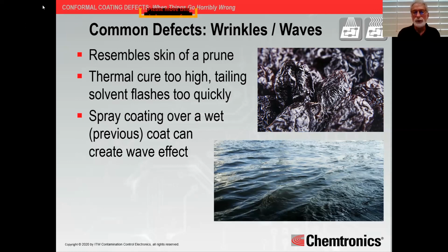And that's exactly what wrinkles look like. They're just real rippled, real wrinkly. And there's a couple of causes of this. One of them is that if you're curing in an oven, or in an IR conveyor system, that thermal cure energy is too high, and that tailing solvent flashes too quickly. In other words, all of your lighter end solvents are flashing, but your tailing solvent is flashing at the same time. It's just too much heat for it to handle. It needs to be done in a staged manner, or you're going to end up with a wrinkly, lumpy mess.